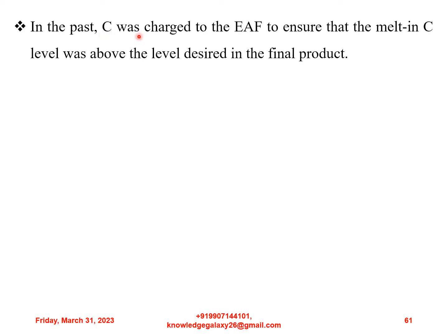In the past, carbon was charged to the electric arc furnace to ensure that the melt-in carbon level was above the level desired in the final product. As higher oxygen utilization has developed as standard electric arc furnace practice, more carbon is needed in the electric arc furnace steel making process. The reaction of carbon with oxygen within the bath to produce CO results in a considerable energy input to the process and has led to substantial reductions in electrical power consumption.